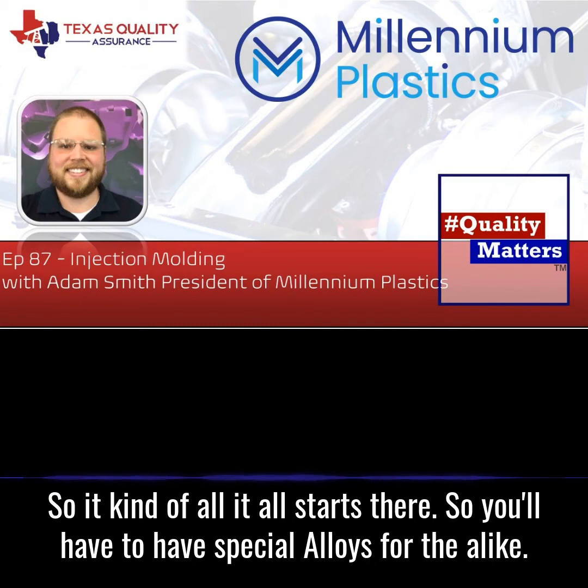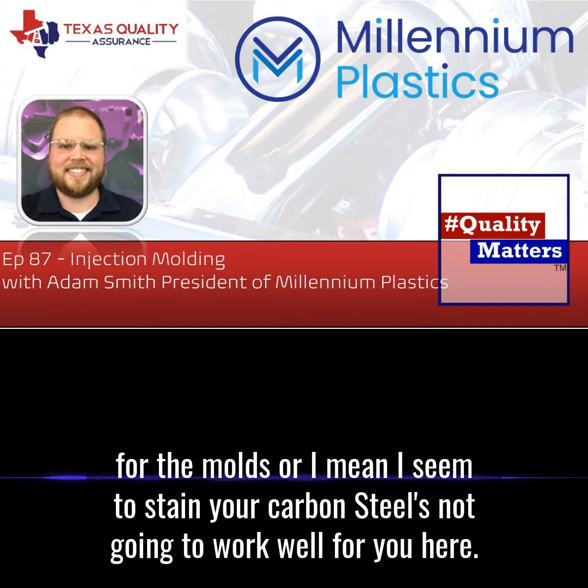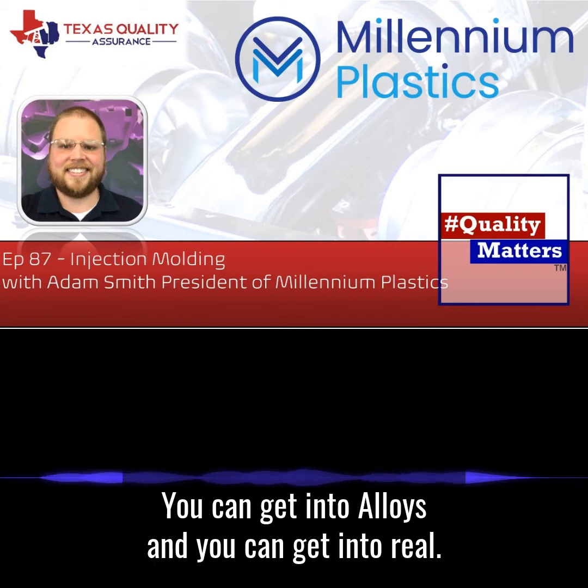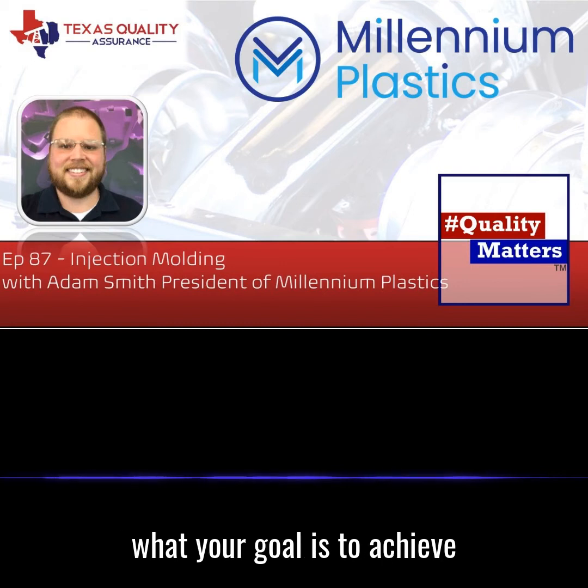So do y'all have to have special alloys for this? It's just fascinating to me. Like, you have special alloys for the molds, or I assume just standard carbon steel is not going to work well for you here. Yeah, I can't just use P20 steel. For high volume, you're using S7 or H13 steels. You can get into alloys, and you can get into some really neat things with different alloys, depending on what your goal is to achieve.